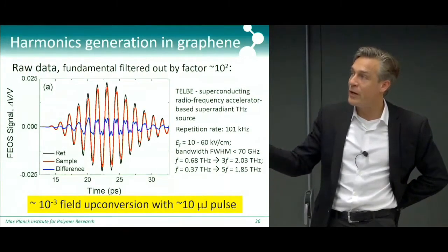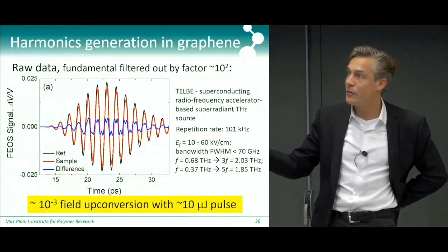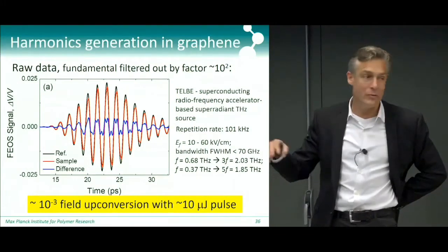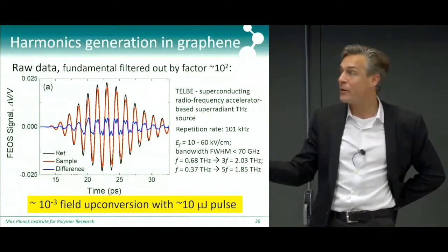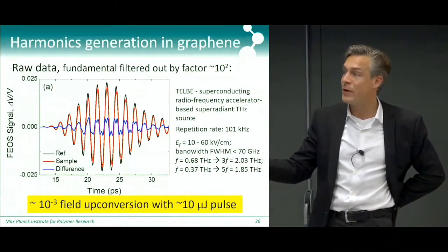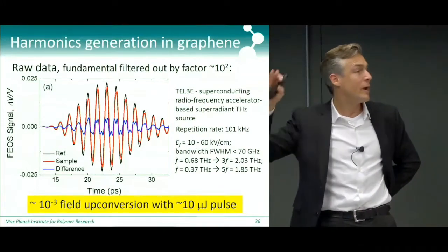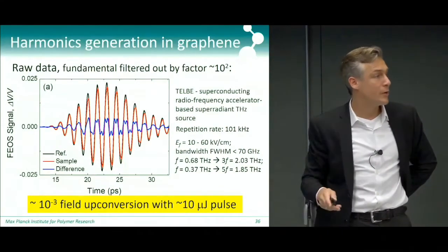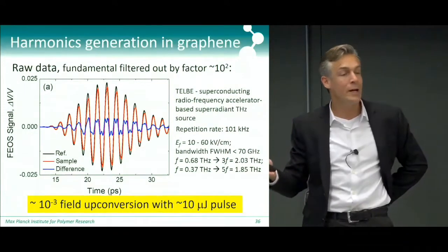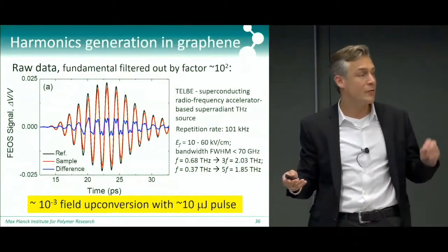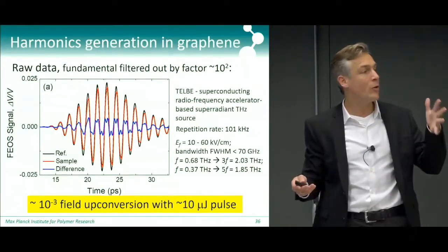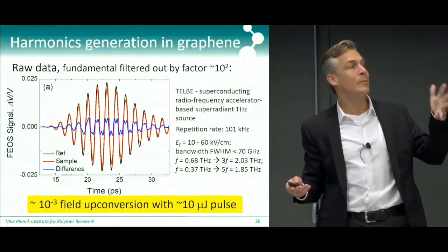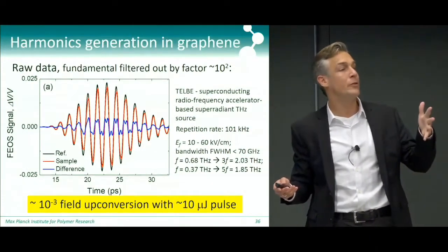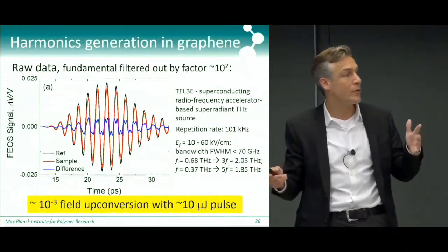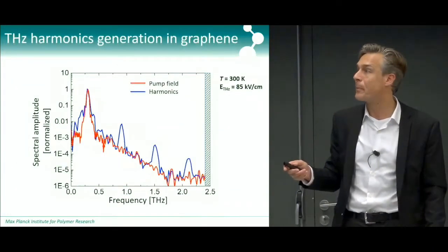So what you see already from this measurement here is that for a 10 microjoule pulse, you get about 10 to the minus 3, 10 to the minus 2 conversion efficiency. So very high conversion efficiency. And you have to realize that this is all occurring in one atomic layer of material. So this is not a bulk crystal, this is just one layer.